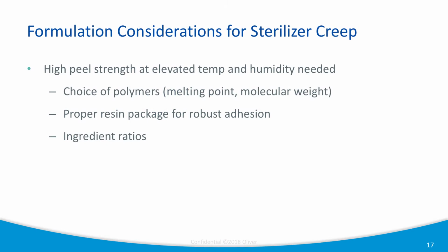And then you need the proper resin package for robust adhesion. That's what we talked about earlier, the tackifier resins. In this case, they need to keep that adhesive stuck under high humidity conditions. So it's really a robustness of adhesion. Sometimes you can have good room temperature adhesion, but under high humidity, the moisture can get to the interface and tend to debond. So you need the right resin for the right substrate. And then, of course, you always have the ingredient ratios for the optimization.